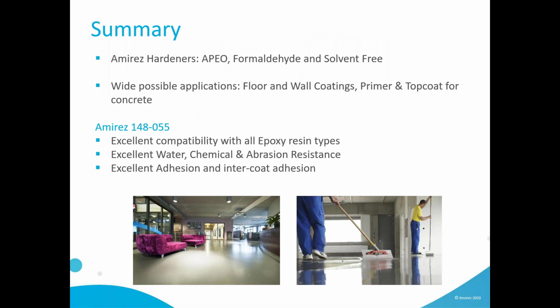To summarize on the water-based epoxy hardener, you have seen from the video that all the hardeners are, I would say, low toxicity with APEO, formaldehyde, and solvent-free. The overall Amirez range gives wide possible application with floor, wall coating, primer on concrete, or top coat. And in the case of Amirez 148-055, you also get a very good compatibility with all types of epoxy resins and pigments, even the very shiny ones or the difficult ones like blue or black pigments. You've got an overall very good water, chemical, and abrasion resistance, and a good intercoat adhesion, which make it suitable to develop a full system based on it. So with primer and then a top coat.